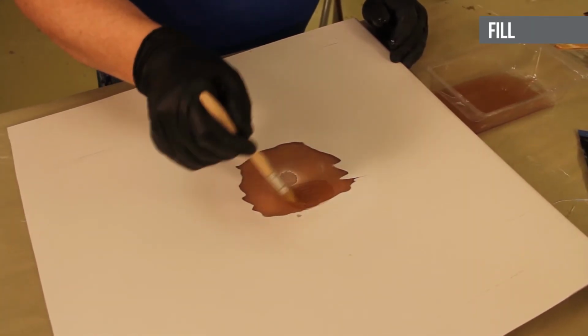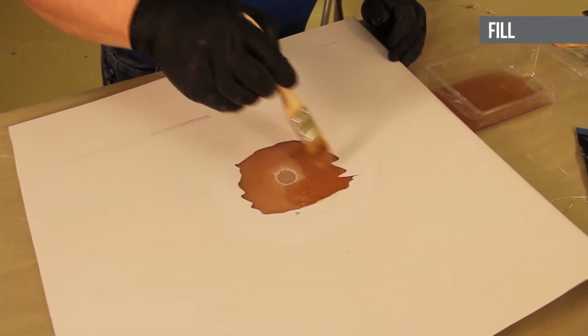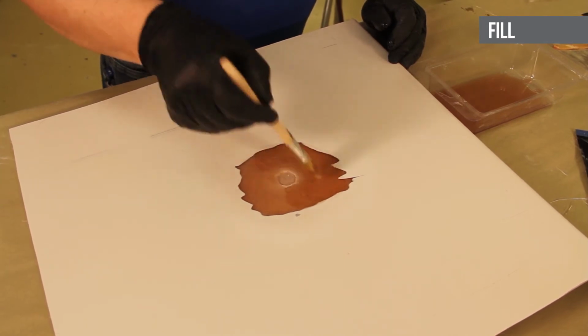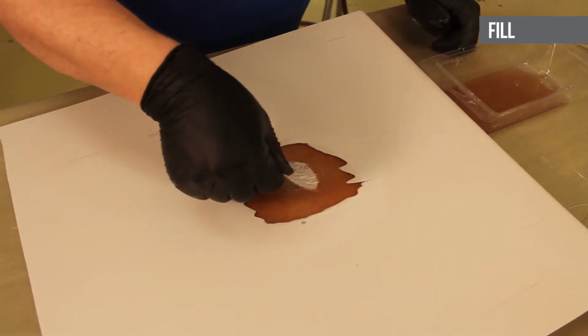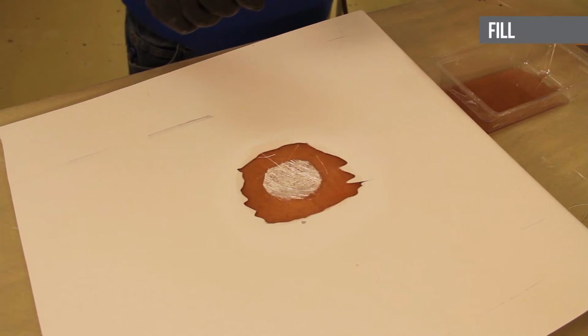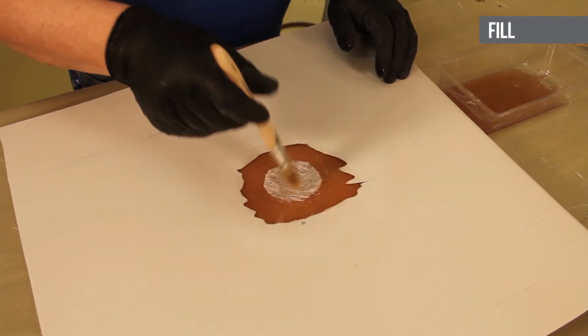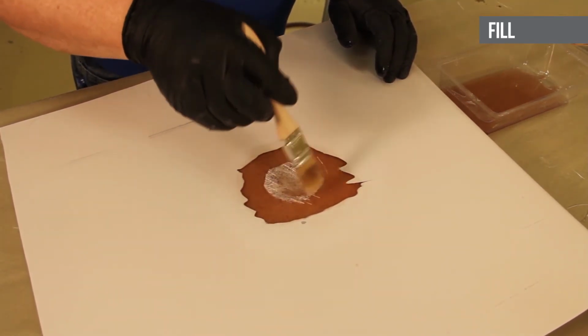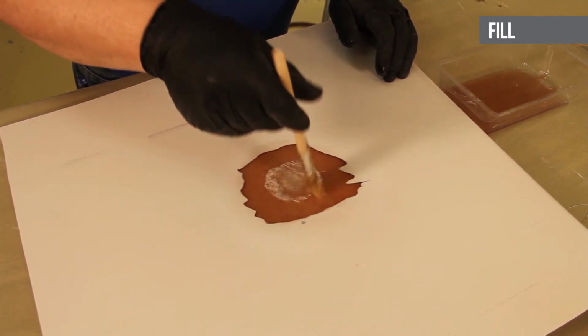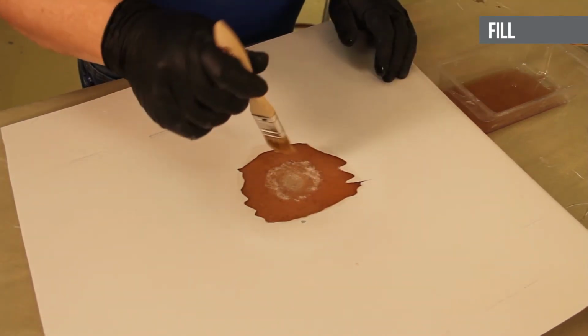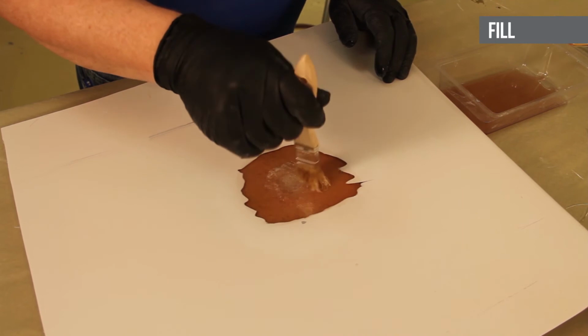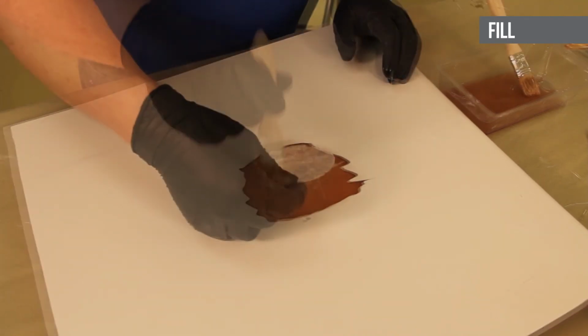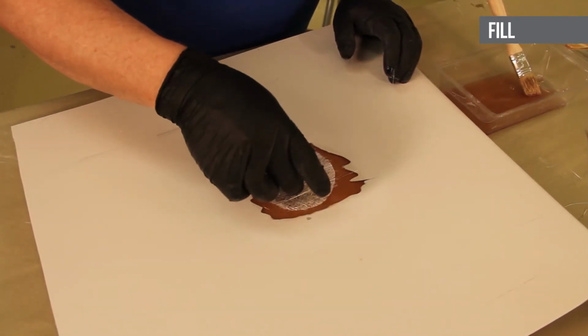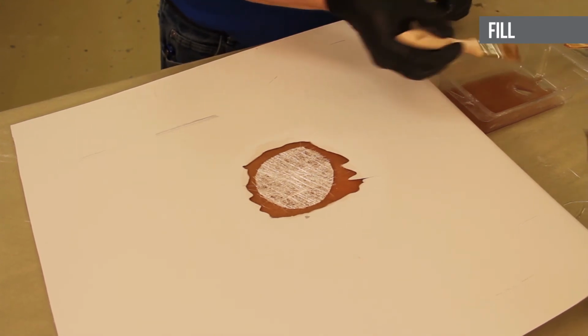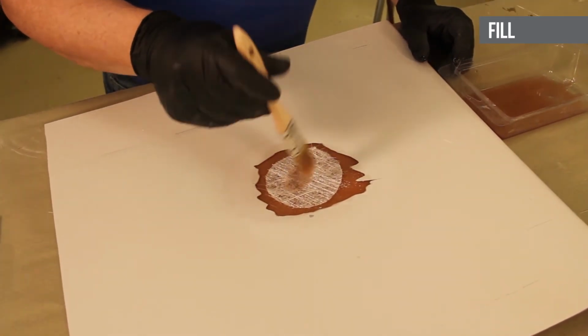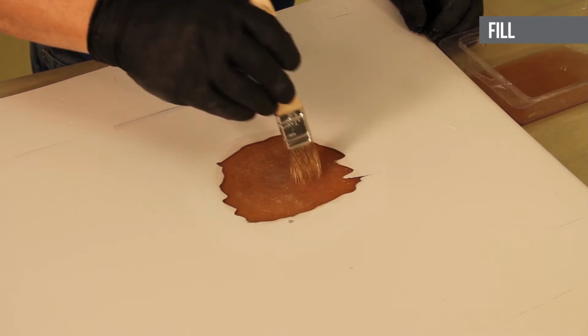Using the included brush, apply the mixed resin to the repair surface. Apply the cut fiberglass mat over the repair and apply more resin. Work the fiberglass resin into the cloth until the white fibers disappear. Additional layers of mat or cloth can be applied before the mixture gels or cures. Any cured resin must be sanded between each layer.